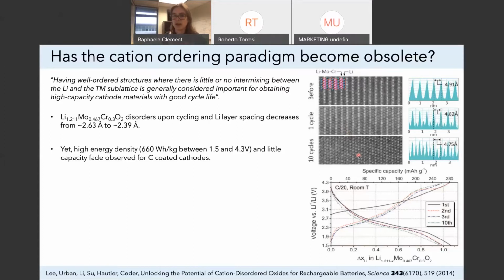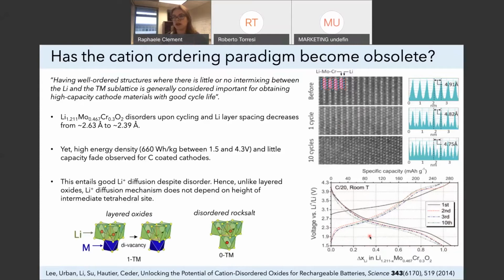However, the surprising observation in this paper was that the electrochemistry is actually quite good. You can definitely see a change from the first charge to subsequent charge-discharge cycles, but the capacity itself isn't fading too much, and you can extract more than one lithium per formula unit. So this is a good cathode despite the disorder. And so what this suggests is that there is a different type of lithium diffusion mechanism in these materials.